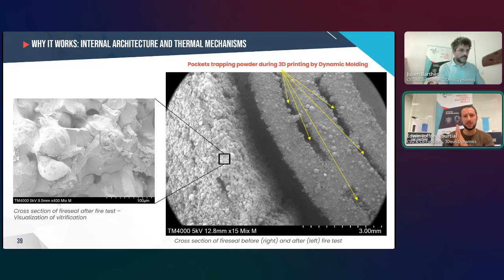What we see here is the microscopic evidence of the mechanism that makes this fire seal effective. On the right, you can observe the initial microstructure of the joint directly obtained from the dynamic molding process. It consists of a silicone matrix intertwined with mineral powder domains, some of which remain intentionally entrapped inside the structure during fabrication. These internal pockets are key to the material's thermal behavior.